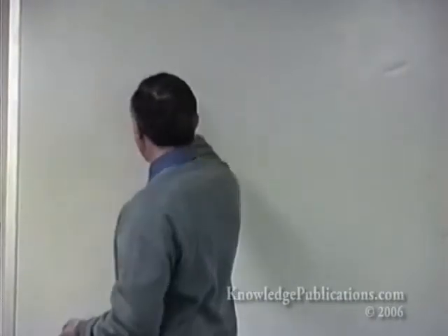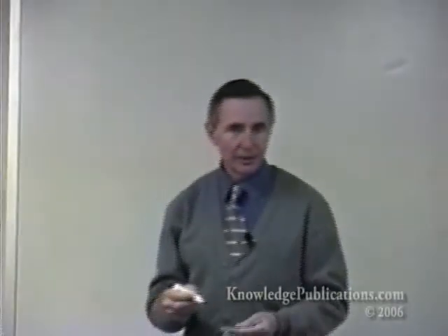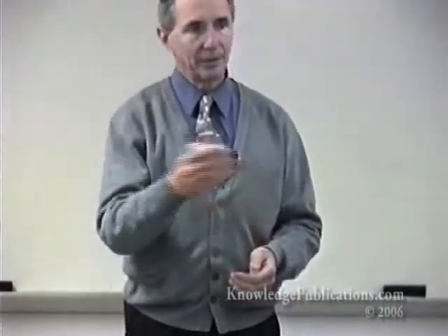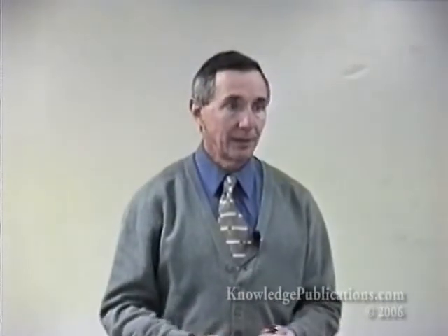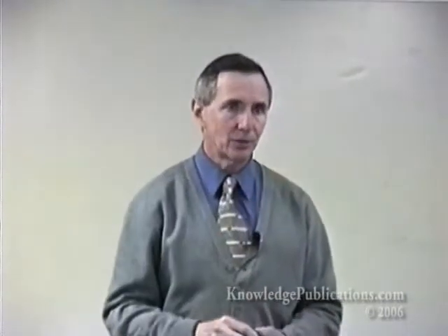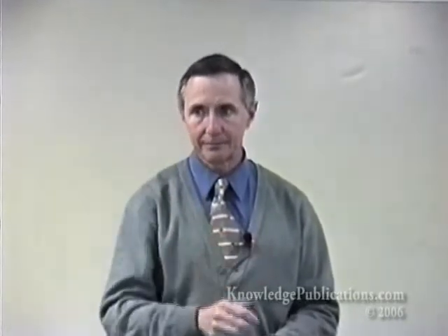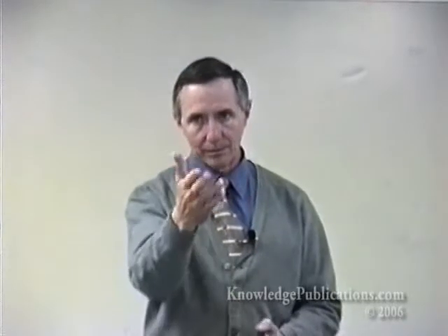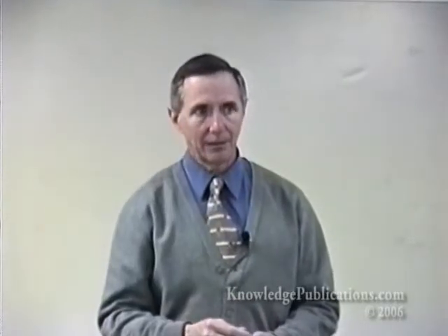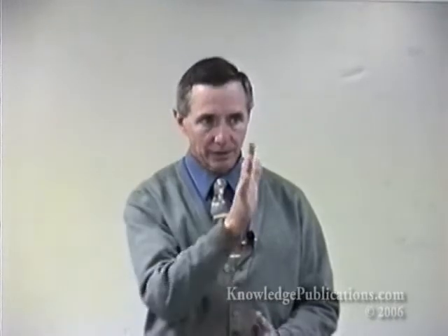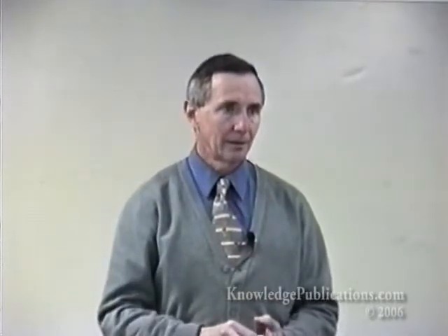The reason that it's a dense medium is that aluminum would like to be aluminum oxide. And the reason it isn't becoming aluminum oxide in this room is because of one reason. It can't gain the activation energy to do so through the oxide. It can't continue to run the process through its oxide. The oxide stops it. If you interrupt that oxide, that aluminum will oxidize rapidly, heat up.